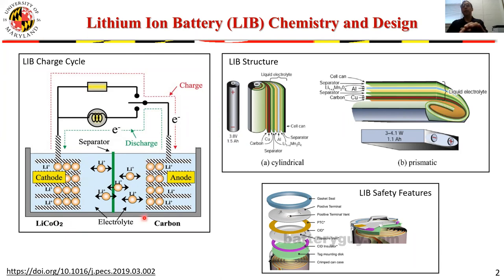The same situation actually occurs on the anode. When you embed lithium atoms into the anode, they end up sitting right next to the organic carbonate electrolyte, which is a weak oxidizer, whereas lithium atoms are a strong reducing agent. So they would also like to react with each other and can produce heat.